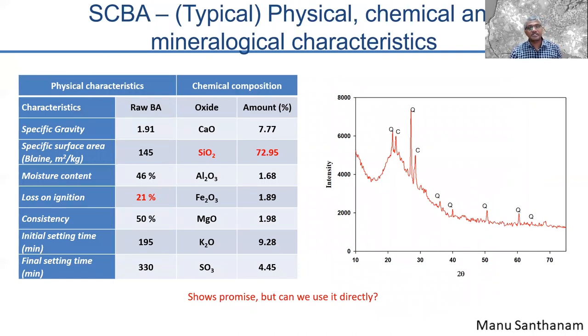If you do an X-ray diffraction analysis, you can get a good understanding of the amorphous component that is present in the mineral admixture. There are obviously some crystalline species also, like quartz and cristobalite, that you can see in the bagasse ash, but mostly you see this large amorphous hump that indicates that a lot of the silica present inside the system may be of the kind that is amorphous, and amorphous obviously means reactive.